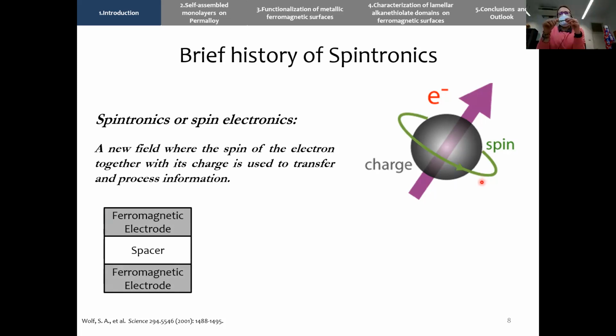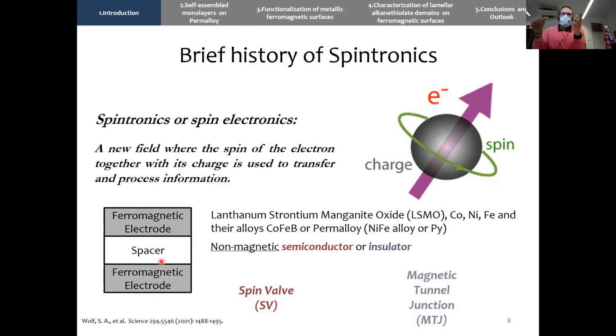The simplest spintronic device is formed by two ferromagnetic electrodes separated by a spacer. For the ferromagnetic electrode, we can have different materials. For example, we can have perovskites, the lanthanum strontium manganite oxides, or transition metals such as cobalt, nickel, and iron, and their alloys. The spacer can be either semiconducting or insulating, and depending on the nature of this non-magnetic spacer, the device will be called a spin valve or a magnetic tunnel junction.